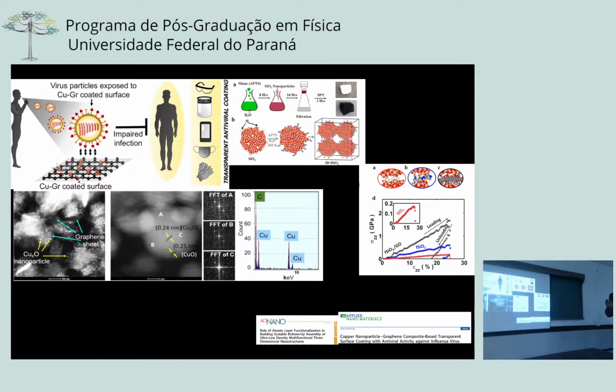Also, you can use this graphene as a coating material. During COVID, this work we started where we wanted to have a coating on top of transparent object. It can be your mobile screen or the shield or glasses, right? Now, the moment you start coating with any object, an antimicrobial or antiviral coating, you start losing the transparency, right? Well, first thing. Second, if you coat with something, if you wash it, it's gone again. So you have to go for coating again because the adherence is crucial as well. Now, graphene being a 2D material and ultra thin, if you coat on all these objects, first, they are going to stick there. Second, the transparency is not compromised, still is the same.